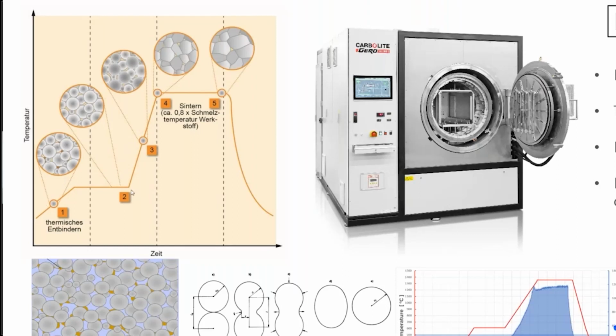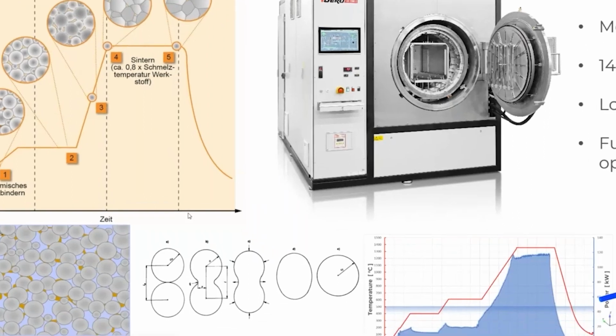So this profile is highly important, and every time we talk about debinding and sintering, you will see such a profile. Because first, the backbone binder needs to be removed between 400 and 600 degrees C. And after this backbone binder is now removed, we need to sinter the part to the final density. So now the powder particles need to sinter together, and this happens 20% below the melting point of the material. That is what you see here, 20% less than the melting point, you have a diffusion process.